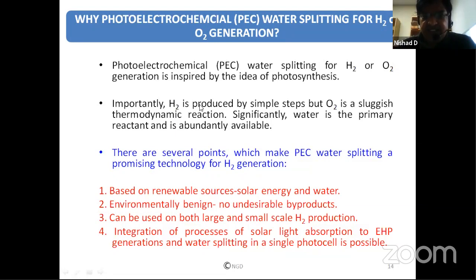So here you can see that H2 production, although a simple step, requires splitting the oxygen from the hydrogen, which is a very sluggish thermodynamic reaction involving almost 4 steps, and you need to overcome the different steps with different energies. This becomes a very difficult aspect. So splitting of water is not a simple mechanism, but with the utilization of optoelectronic devices, you can do this very well and very easily.